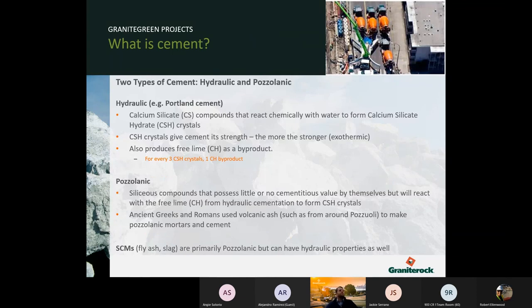So two types of cement, like we covered before: hydraulic, which reacts with water, and pozzolanic, which reacts with the hydraulic reaction. In hydraulic cements, it creates calcium silicates that react with water to form calcium silicate hydrate crystals, which are the crystals that we talked about in the beginning. That's what gives the concrete strength, and it does give off heat.